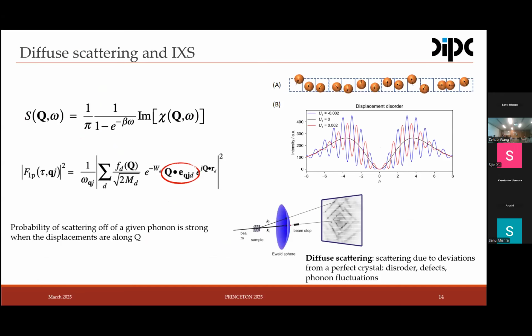What I'm trying to do in my work is essentially studying the origin and the mechanism for the stabilization of the charge order in these Kagome metals. For that, I mostly use diffuse scattering and inelastic X-ray scattering. Diffuse scattering is nothing else than normal diffraction, but instead of focusing on long-range order, like measuring Bragg peaks, we focus on short-range correlations that appear as precursors or pre-transitional fluctuations of a charge order phase transition at lower temperature.